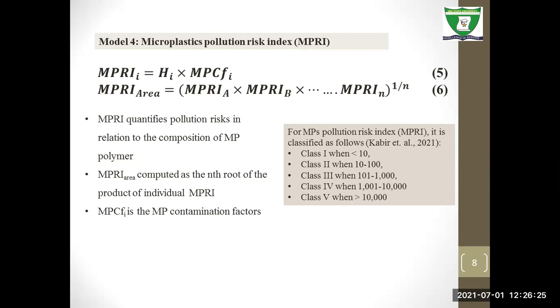Yes, the number of samples you are working with. So this quantifies the pollution risk in relation to the composition of the microplastic polymer. From the results you obtain, you can classify them: class 1 when it's less than 10, class 2 when it's 10 to 100, class 3 when it's 101 to 1,000, class 4 when it's 1,001 to 10,000, and class 5 when it's greater than 10,000. This is according to Kabir et al., 2021.